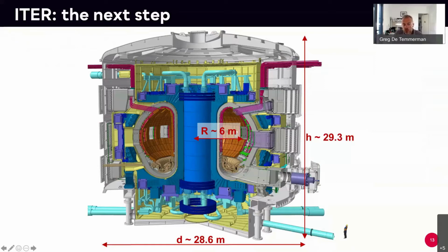And then the machine which is supposed to demonstrate that is what we call ITER, which is a big scientific project going on in the south of France, near Marseille or Aix-en-Provence, if you know. And this is typically the size the machine will have. It's about 30 meters in diameter and 29 meters in height. So it's a pretty big baby. The plasma volume is about 1,000 cubic meters, and it's supposed to demonstrate that we can control a fusion plasma and we can generate 10 times more energy out of the fusion process than we inject into the plasma.